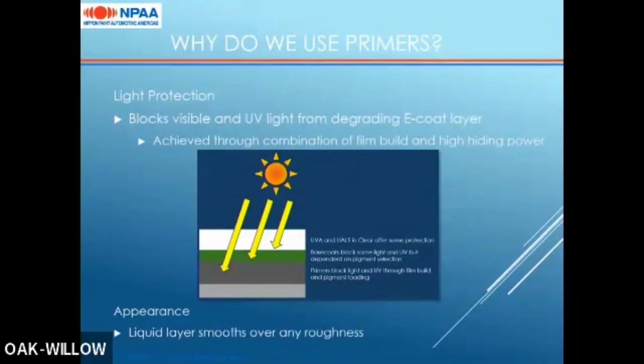As you can see in this graphic, most coatings, again, being derived of the primer, base coat, and clear coat layer, the clear coat provides protection against the UVs with UV additives and HALS. The base coats then also block some light and UV, but it's very dependent on the pigment selection. So a lot of reds and whites won't protect as well, whereas the primer helps protect against all the rest of any light penetration down to protect the E-coat entirely.